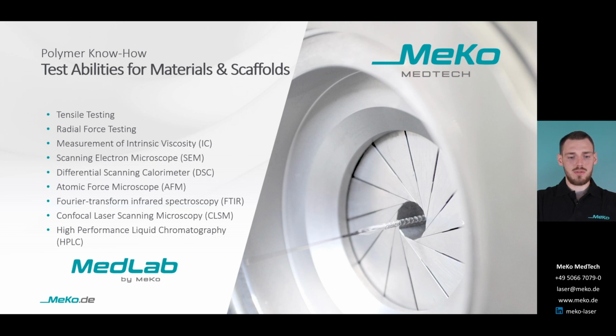As we already learned from Zeus, oriented polymer tubing is designed to have differences in strength and elongation when we compare the axial to the circumferential direction. The final scaffold can be tested using a radial force testing setup, simulating the crimping behavior into the catheter and the radial force after balloon-assisted expansion and deployment. And this is what you see here in the picture on the right side.